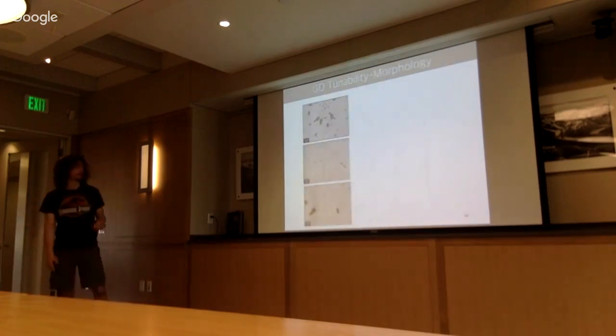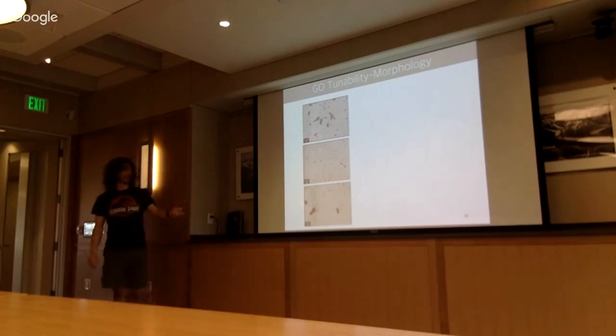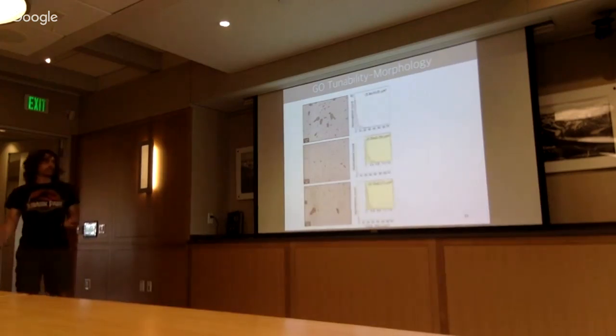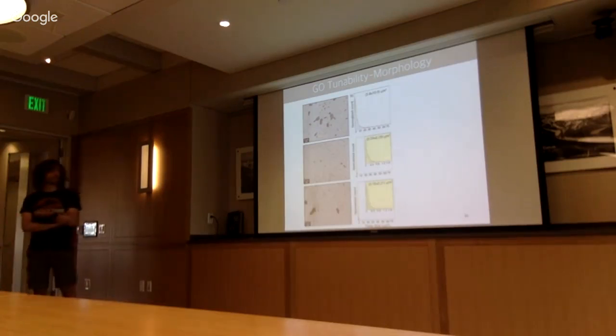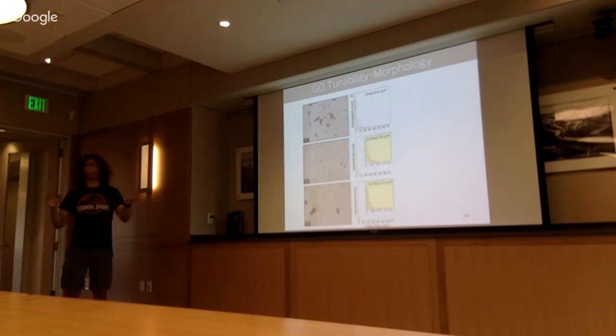So here I show you that we can tune the chemistry, but you can also tune the morphology of the material. Here I'm just preparing a material. The scale bar is the same. So I prepare a material with large flakes, I can prepare a material with small flakes, or a material with small and big flakes. And through quick image analysis, we can check the size distribution of the material. It follows a log normal distribution. And here we have about 5 micrometers square flake size. Here we have sub micrometer square flake size.